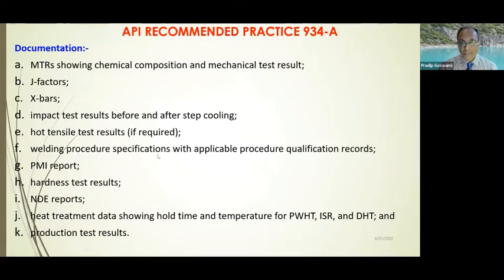We require the welding procedure specification and all the reports related to welding procedure qualification to be submitted. The PMI, positive material identification test reports for the welds and base metals at various stages of production. You need the hardness test results. You need the NDE reports. You need the heat treatment data, which includes the post-weld heat treatment, ISR, intermediate stress relief, and the DHT, dehydrogenation heat treatment, if adopted. And last of all, the production test results also.